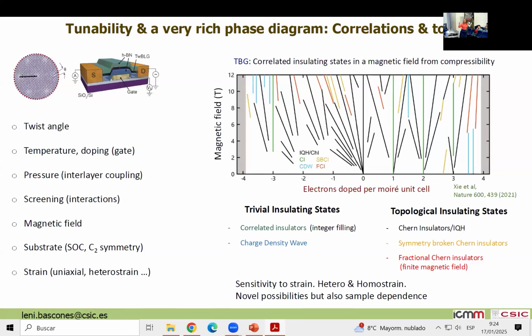Well, this dependence is not so much associated to Zeeman, but to orbital magnetism. The idea that we have from graphene, we have to put it away, because one thing that makes graphene non-magnetic is that you don't form local moments because your bands are very wide. Here they are going to be very, very thin. So really in this system, people have in some cases observed real magnetic state, complete full polarization. But as I say, the magnetism is mostly associated to orbital magnetism. The way that you see it depends on the topological states. It's really associated to currents.